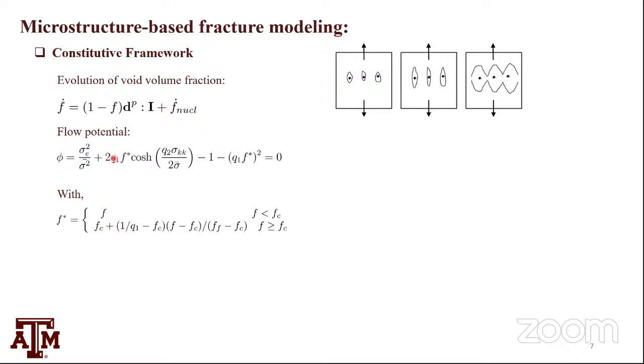When f enters here, you have the flow potential that starts to shrink. When f grows, the flow potential starts to shrink. And if f is greater than some critical value, then this growth of f star becomes asymptotic or near asymptotic. That causes the collapse of this yield function rather rapidly. Before we go on, simple, if this f star goes to 0, you reduce back to a von Mises flow potential. This is actually a flow potential, so I should not have used the equal to 0 sign, but we have it there, like a yield function.